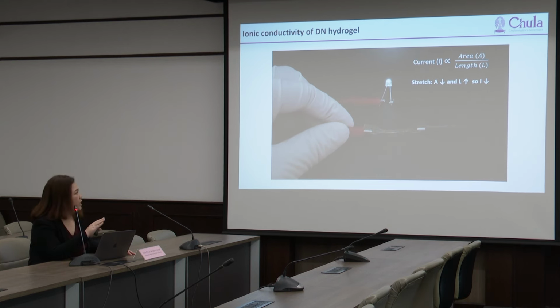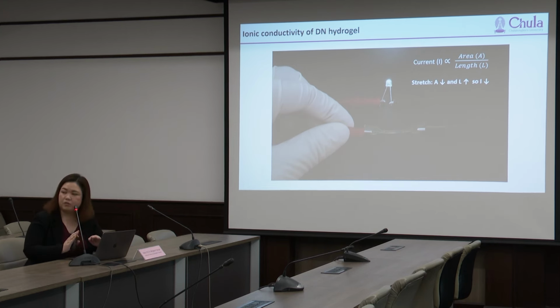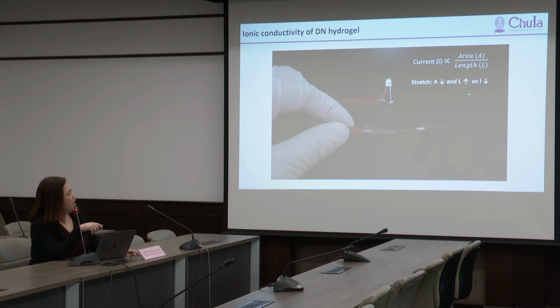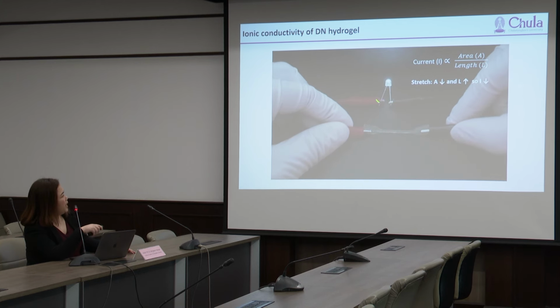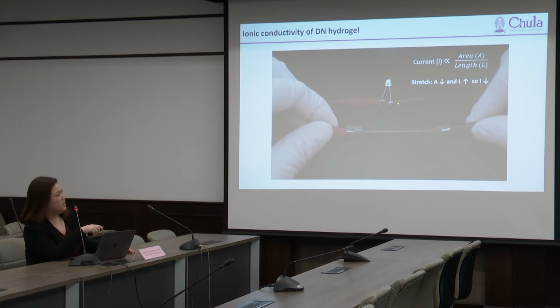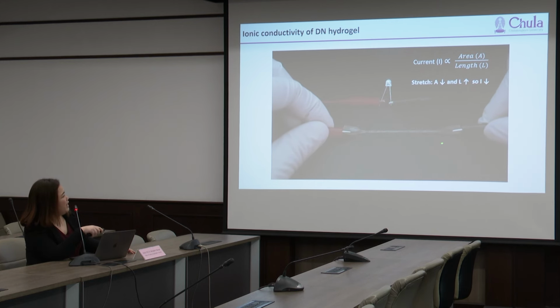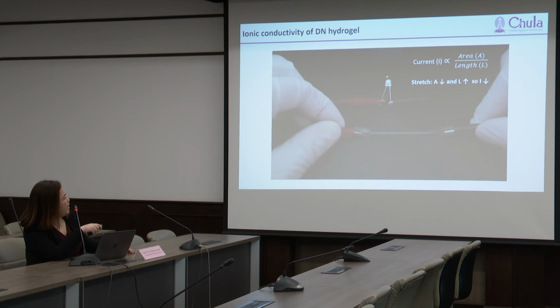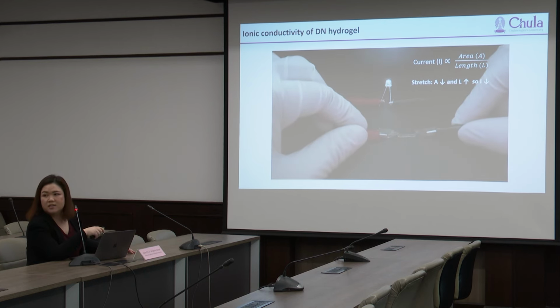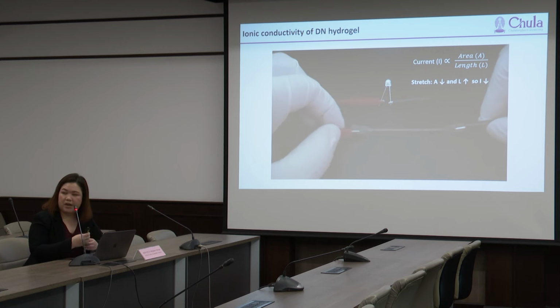Another thing that I would like to test here is what happens when I stretch the dog bone. Basically, if you look at this equation, you can see that the current is proportional to the cross-sectional area and inversely proportional to the length. So when I stretch the dog bone, the cross-sectional area will drop, the length increases, and the current will drop. And you can see from here that when I stretch the dog bone, the brightness of the LED light decreases. See? And then when I relax the dog bone, the brightness goes back to the original status. So you can see that we can track the movement here.